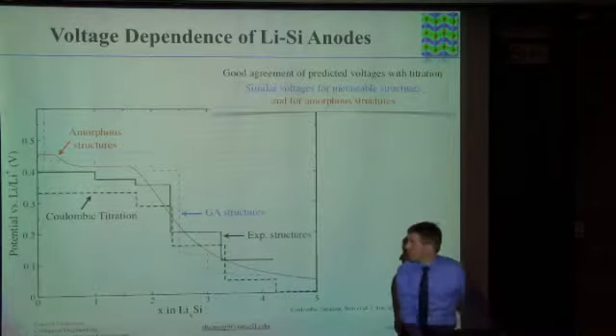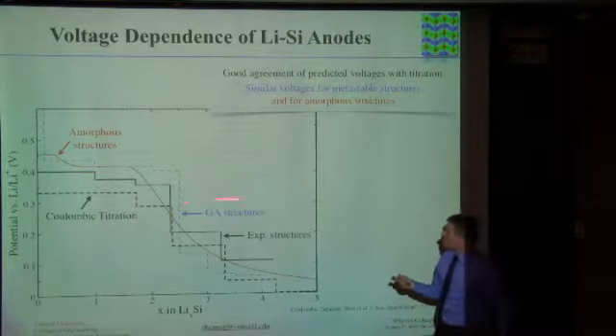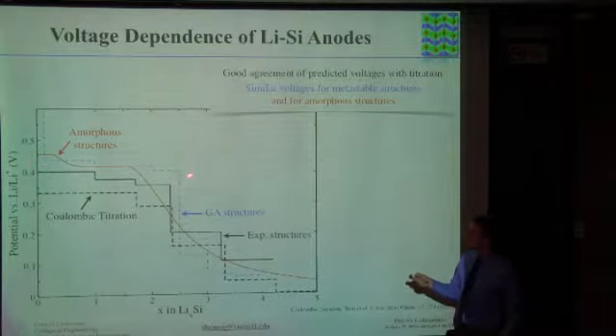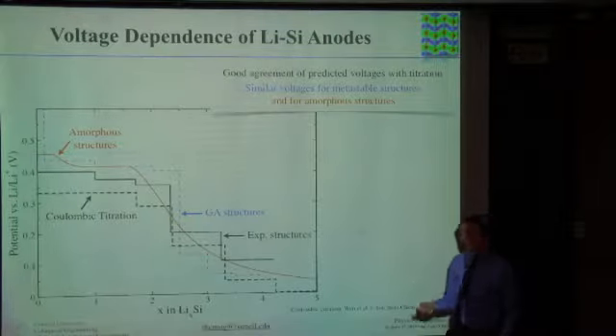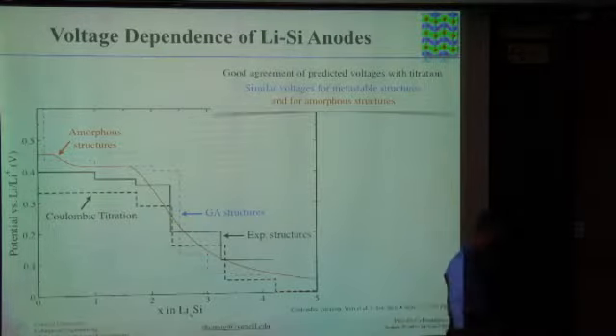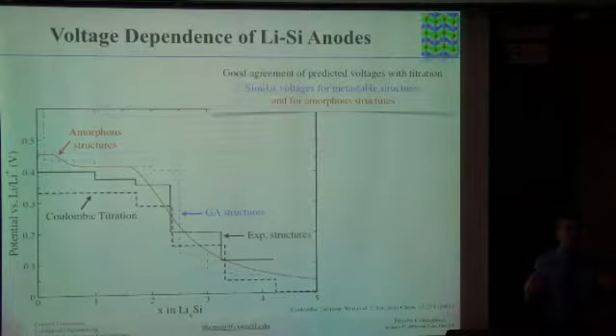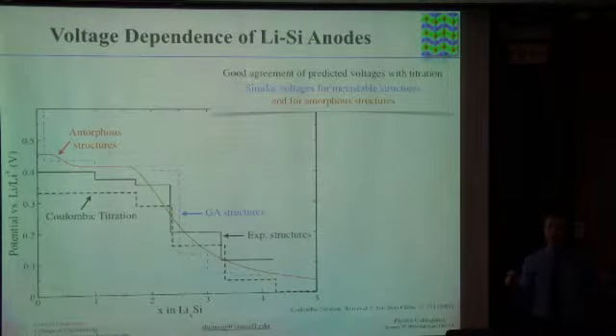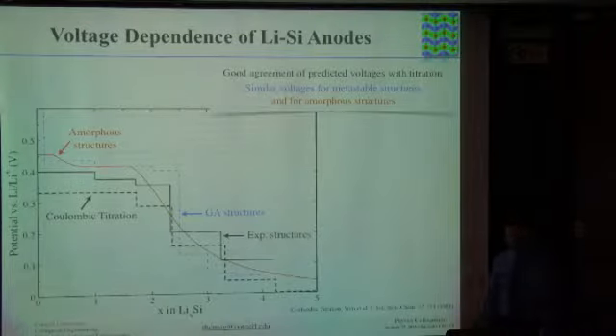If we now look at what our genetic algorithm structures would have given us, the deviation is a little larger, but not terrible. It's probably still within the 50 to 100 milli-electron volt, so still very useful. What that means is we can use the genetic algorithm, and even if we do not find the ground state crystal structures, even if we find just some small unit cell representatives, we still have a good representation of what the energy landscape overall is and what the energy is as a function of composition. And we can use that to pre-screen potentially new battery materials.